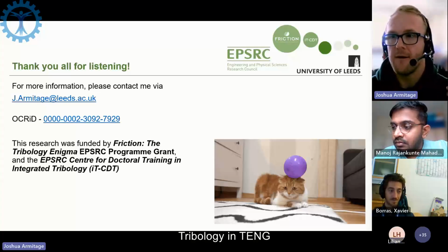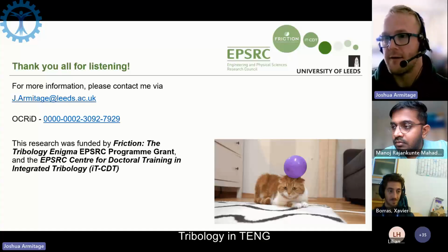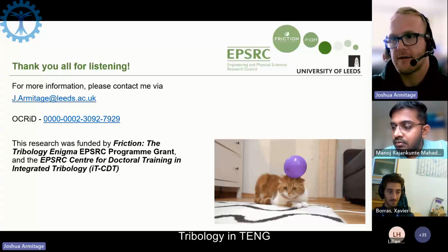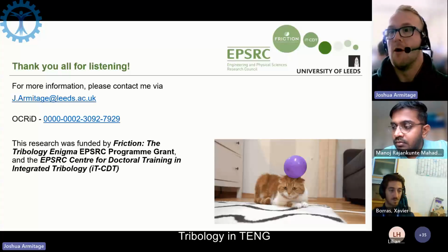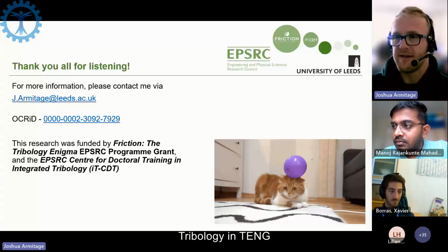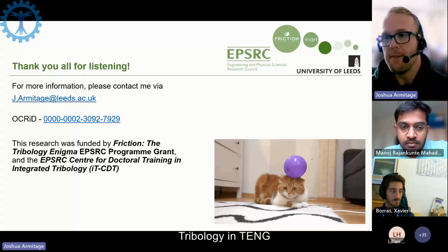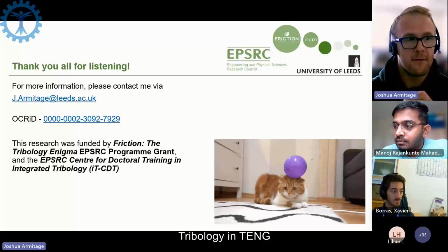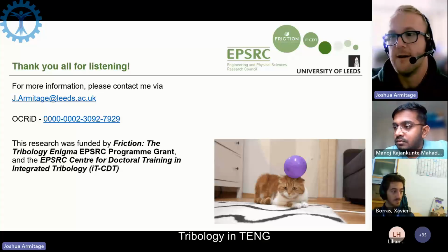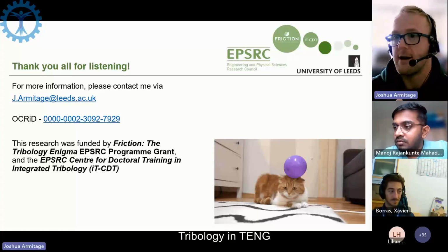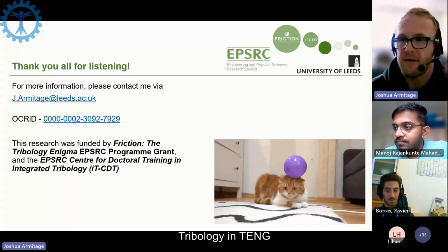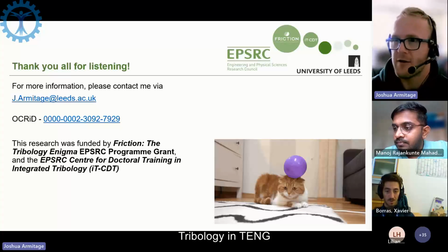You're diversifying the spectra of electrons that are in states of the donor surface. So you have more electrons in high energy states, but conversely you have more unoccupied energy states within the other material that might be lowering in energy by stretching or compressing bonds. So in a nutshell the best way to describe that is through the flexoelectric effect, and that's purely through having a strain gradient in a material inducing a change in surface potential, from this modification of the physical structure leading to a change of the electronic structure, if that makes sense.